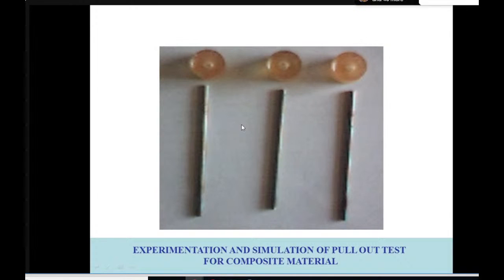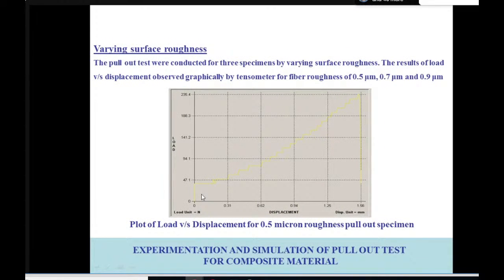Now this pull out gives you the idea of what the strength at the interface is, what the bonding between fiber and matrix is. We presume there is a perfect bonding between fiber and matrix, meaning theoretically there will be no failure at the surface. Either the matrix fails or the fiber fails, but in real life it may not happen. So to evaluate this, we measure the bonding strength by pull out test. You may be able to see this yellow colored graph: this is load versus displacement for 0.5 micron roughness for a pull out test specimen.